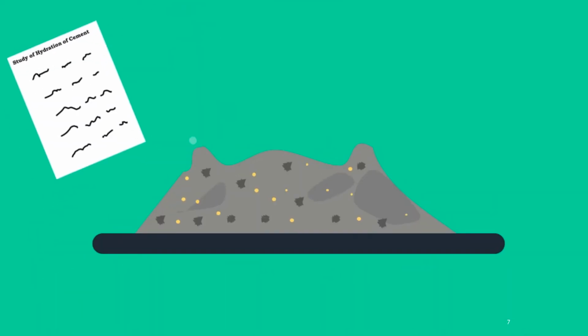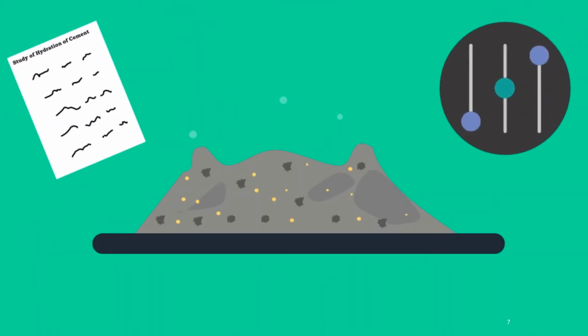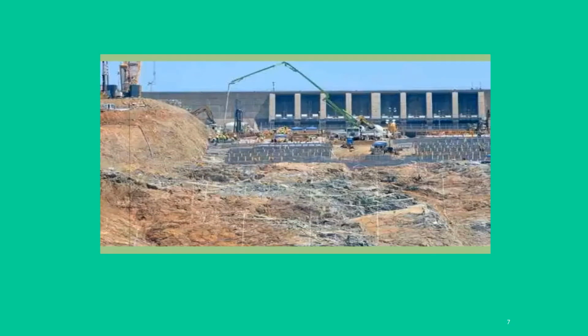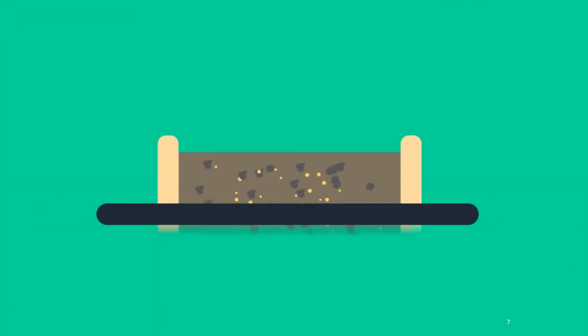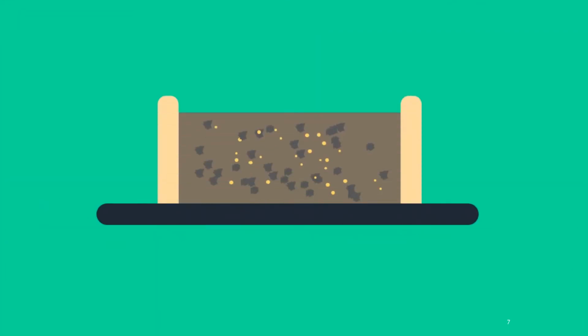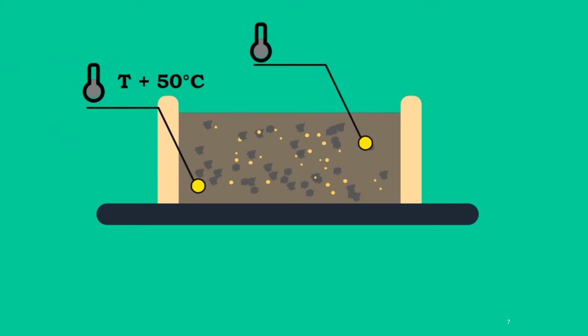The study and control of the heat of hydration are important in the construction of concrete dams and other mass concrete constructions. From past experience, the temperature in the interior of large mass concrete is 50 degrees Celsius above the original temperature of the concrete mass at the time of placing, and this temperature is found to persist for a prolonged period.